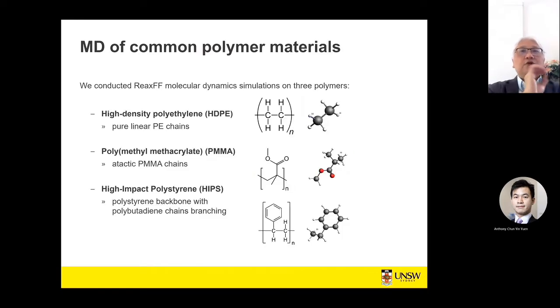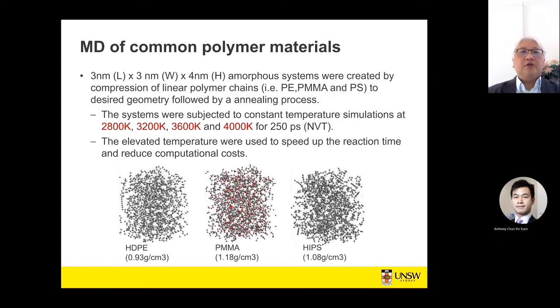And what we have done here is that we took another step to try to understand whether we could look at typical polymers, for example, high-density polyethylene, PMMA, or even high-impact polystyrene, and look at how they degrade when the material is subjected to a high temperature. So in order to do so, we took the amorphous system of these various polyethylene, polystyrene, and PMMA. We subject it to a temperature that is close to the breaking of the bonds, which is roughly above 2000 K, right? And based on that, we can now see what other compounds it will form once the molecules break.